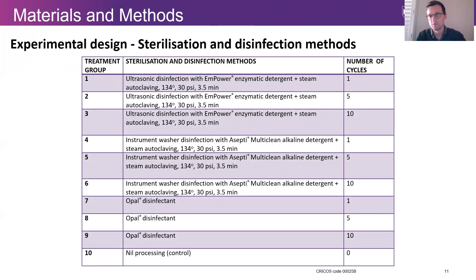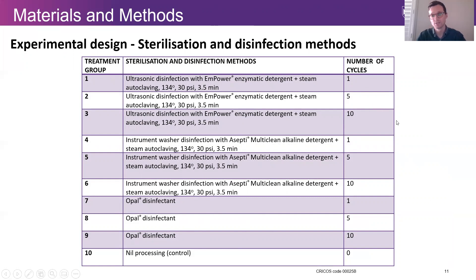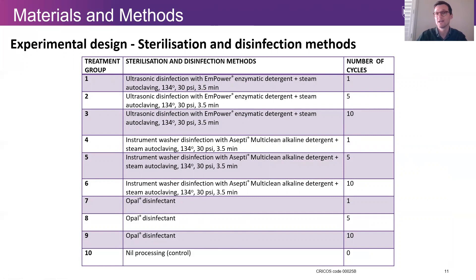The experimental design for my study is as follows. We broadly have three treatment groups: ultrasonic disinfection followed by heat sterilisation, instrument washer disinfection followed by heat sterilisation, and a medical grade opal disinfectant. Each of these broad categories undergoes one, five, or ten cycles, and this is done to replicate what we might see in private practice. So under each of these competing sterilisation and disinfection protocols, particularly with increasing number of cycles, do we see any differences in the crown materials? That is the question.